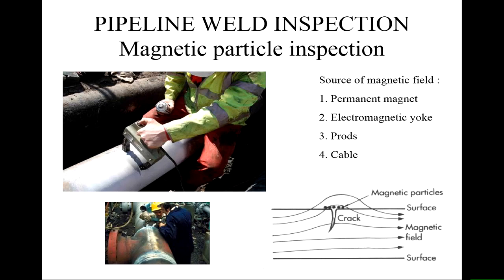And it's been painted white so you can see the magnetic particles when they're added. So what happens is you get these magnetic field lines that run through the material. And in an ideal case, where there's no defects, they will be within the material and very little escapes at the surface. If there's a crack, then we get what are called fringing fields, these magnetic fields which come outside of the material and flow around the crack, because there's this non-magnetic anomaly there, and the magnetic field lines have